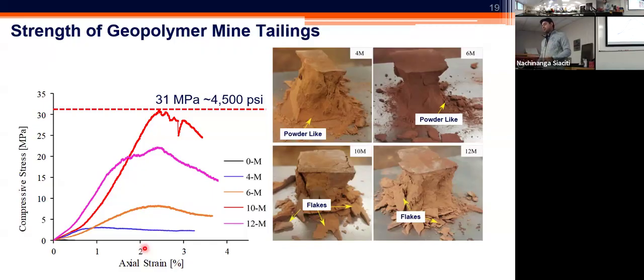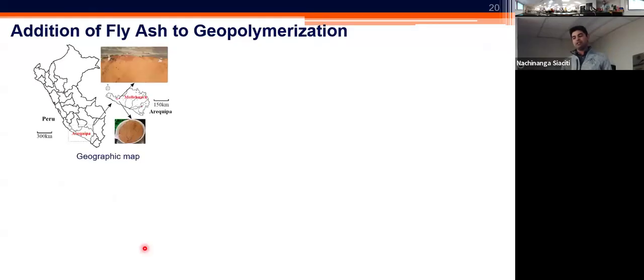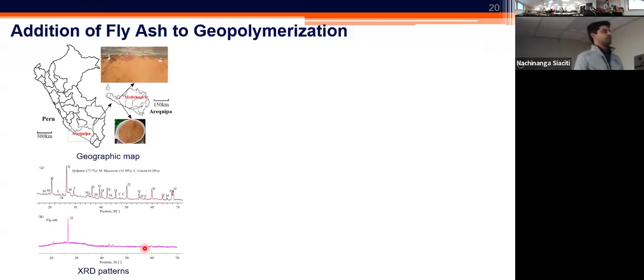So the next step in terms of the evaluation has been to see if we have this consistency in terms of the behavior for this material. So we did a lot of testing for many of these mine tailings, and realized that the strength that we were getting was not sufficient. So then we went back and looked at the elemental composition, realizing that in some cases the silicon to aluminum ratio was not necessarily favorable. So we did attempt to amend and supplement that by adding some other types of waste material.